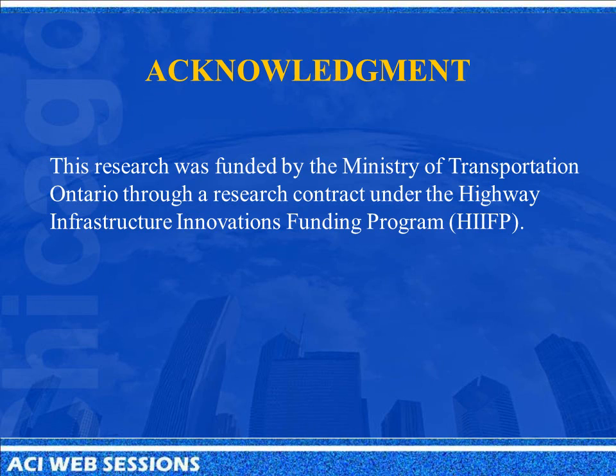I got a quick question. You indicated that those environmental effects had a result on the creep performance. Do you have any information whether these specific products you were using did already have a moisture influence on the short-term behavior? And if yes, to which extent? To the same extent, larger or smaller extent? Well, basically, all three products, their manufacturers state in their product sheets that they're moisture resistant. So in terms of long-term, they shouldn't have an effect. But according to our test results, they do.